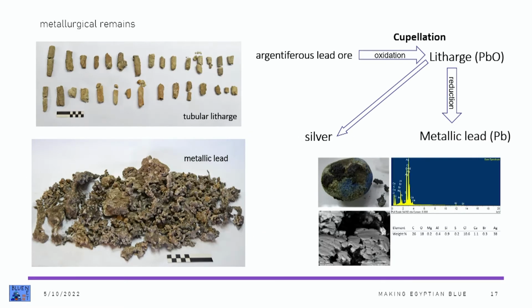Beyond the pigments, litharge rods, that is lead oxide rods, as well as amorphous metallic lead lumps were found at the site, indicating that metallurgical processes were carried out, including the reduction of lead oxide to metallic lead. And possibly this lead source could have been used also for pigment production.